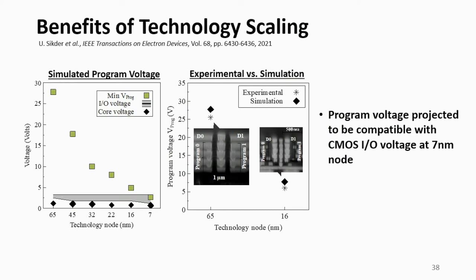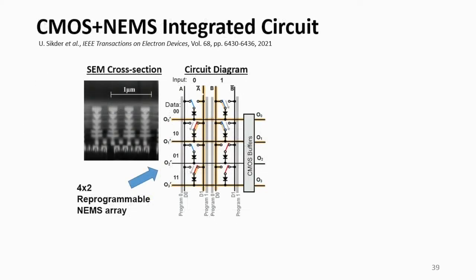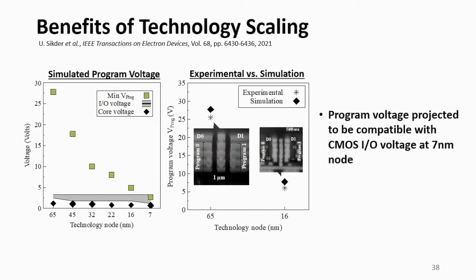Now, the benefit of transistor scaling or CMOS technology scaling is that you bring metal pitches down with each new generation. So the smaller the air gap, the more electrostatic force that you induce when you apply a voltage. So this allows you to lower the actuation voltage of these mechanical switches. And so the plot in the middle here just shows measured switching voltage versus simulated switching voltage to verify that indeed the operating voltage of our mechanical switches is scaling as we expect. And we project that by the 7 nanometer technology node, the metal pitches and the air gaps will be so small that the voltages needed to actuate these switches will be perfectly compatible with CMOS transistors.